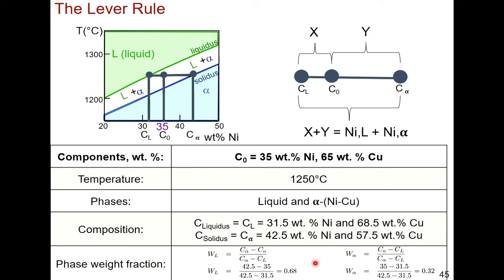Okay, so how much liquid do you have in your system? Well, at 35 weight percent nickel, that's your C naught, you draw the tie line, and it intersects the liquidus, Cl, at 31.5 weight percent nickel, and your C alpha you read off of the x-axis here at 42.5 weight percent nickel. And then if you plug it in, you get the weight fraction of liquid is 68%, and thus the weight fraction of your solid is 32%. So right at 35 weight percent nickel, 1250 C, you have 68% of your system still in liquid form. It hasn't fully solidified yet. And then 32% is in the solid form already. It's already started to solidify, right? So let's go through that. So you're in the liquid form, right?